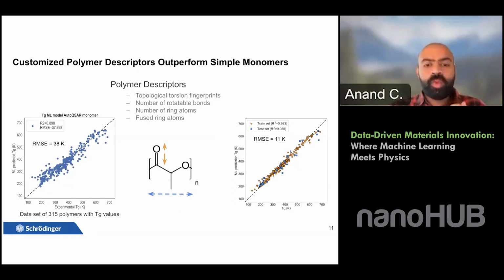However, if we provide some custom polymer fingerprints, for example, topological torsion fingerprints for these polymer repeat units, which were normalized with respect to the repeat unit. So as the polymer repeat unit becomes bigger, your fingerprints don't change, because we are dealing with large molecular weight polymers here, and your polymer property should be invariant to the repeat unit representation. We also put in some additional descriptors like the length of the side chain and the backbone, and the number of fused ring atoms, which change the polymer chain stiffness. Once we do that, we can bring down the root mean square error considerably from 38 Kelvin to around 11 Kelvin. So these descriptors can be generated very easily using our tool.